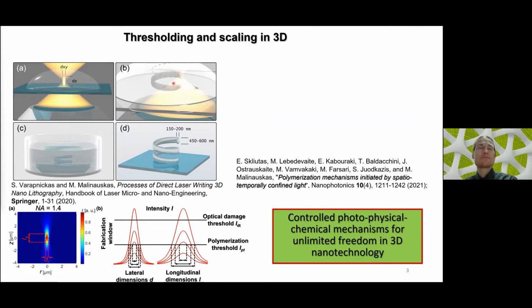After writing the structure, we put the sample into the developer, a wet chemistry procedure, and all the unexposed material is washed out. The liquid developer can be acetone, pentanone, isopropanol, ethanol, or sometimes even water. It depends on the material. And thus, we get a revealed 3D structure, which follows the beam scanned path.